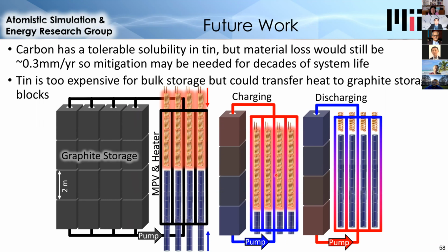So for example, in the charging case shown in the middle, if you pump tin up through the heaters, it can be heated and then deposit that heat in the graphite. When heat is needed, the hot tin can be pumped out and the heaters can be replaced with the PV cells generating electricity. Now, although the solubility of graphite in tin is much lower than silicon, it still would result in about 0.3 millimeters of material loss per year, which may be too much for decades of life.